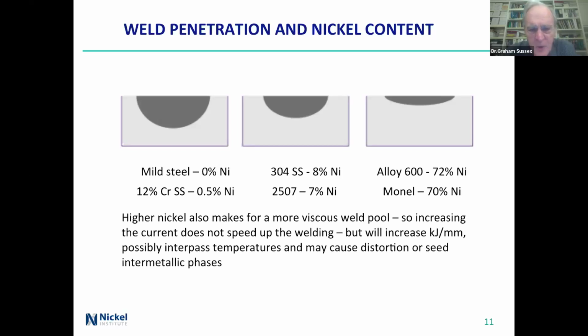So the higher nickel basically makes the weld pool more viscous as well. So if you put the current up because you think it's just not quite hot enough, it won't do anything except heat the whole thing up, and it'll take longer to cool down, and you may get issues with, at high temperatures, forming phases that you don't want. You'll have the interpass temperatures go up, and you might get distortion. And the seed intermetallic phases is something that I've actually mentioned as well.